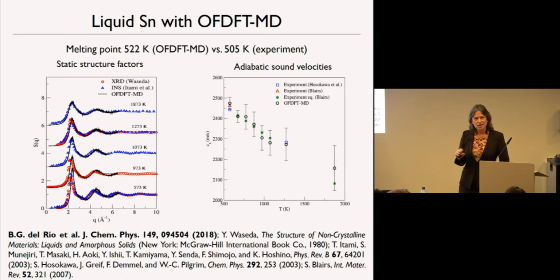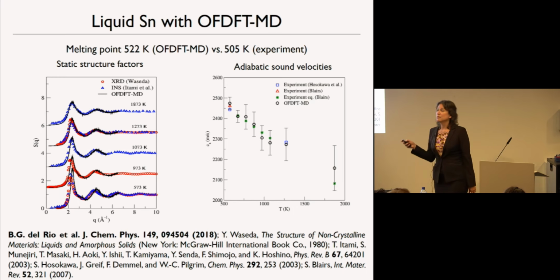We're in the process of doing liquid gallium. But let me just say again, I'm not showing you the results here, but we calculate a melting point that's in pretty good agreement with experiment. Static structure factor is in good agreement with experiment. Adiabatic sound velocities, the black circles are orbital-free DFT. The rest is experiment. So we can do quite a good job describing liquid tin.